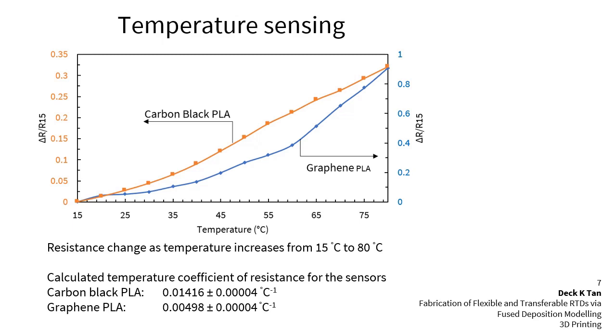It is shown that the carbon black PLA sensor had a sensitivity of around 0.014 per degree Celsius, whereas the graphene PLA sensor had a sensitivity of around 0.005 per degree Celsius. As shown in the graph, the increase in resistance with temperature for the carbon black PLA sensor was more linear than the graphene PLA sensor.